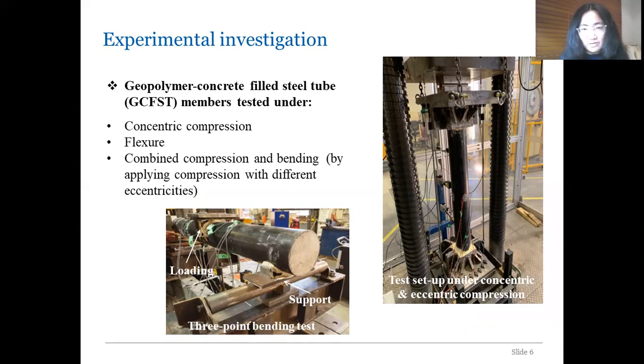In the experimental investigations, we prepared a number of geopolymer concrete filled circular steel tube members, and we tested them under different types of loading. We tested one under concentric compression, one under 3-point bending using the test setup shown in the photo at the bottom, and we tested a number of specimens under combined compression and bending by applying compression with different eccentricities to generate different bending to compression ratios.